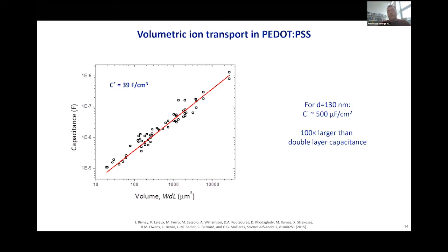Just to throw some numbers here and create a calibration point, if you have a film of this material that is only 130 nanometers thick, you will have a capacitance per unit area that will be two orders of magnitude higher than what you would get with a gold electrode of the same area. That means that now you have two orders of magnitude stronger coupling between ionics and electronics, which also means that you can now make your electrodes two orders of magnitude smaller, 100 times smaller, and still be able to record with the same signal to noise ratio. So by just adding a thin film of a conducting polymer on your electrode, you are able to increase the coupling, the communication between the two worlds, and gain in spatial resolution.